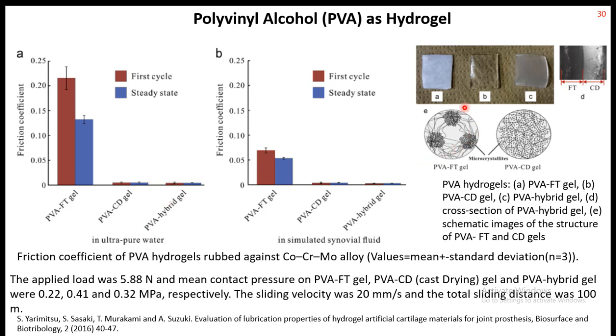These changes were because of the structural changes here. For example, PVA freeze-thaw process gives these kind of microcrystallites which are aggregated at some places, whereas in the case of PVA CD gel, we have got these microcrystallites which are uniformly distributed throughout. Because of this, PVA CD is transparent, whereas PVA FT is opaque. So there is a difference in the crystalline structure, and overall PVA hybrid gel, that means a combination of FT and CD, gives a better result. So PVA hydrogel is another choice we have, other than PEEK and UHMWPE composites.